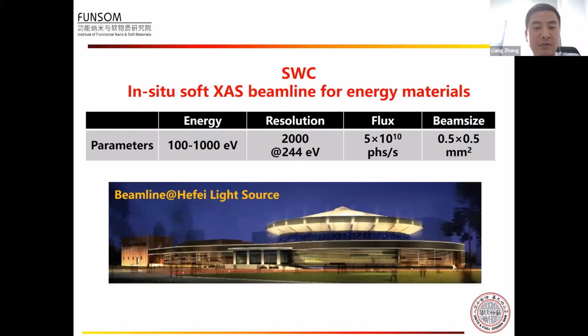As I mentioned, our center also tried to develop some new synchrotron radiation capability. Therefore, starting from 2014, I think, we planned to build a new beamline at the Hefei light source, and this beamline is mainly used for the in-situ soft XAS study for energy-related materials. The energy range for this beamline is between 100 and 1000 eV. The resolution is about 2000 at 244 eV, and the flux is 5 by 10 to the 10 photons per second. This is a bending magnet beamline, and the Hefei light source is actually a second generation synchrotron, so the flux is not very high.